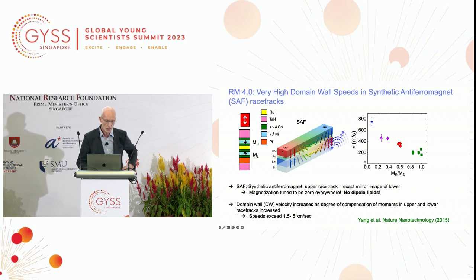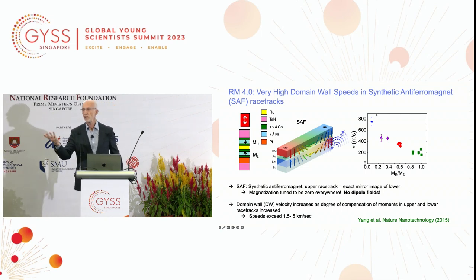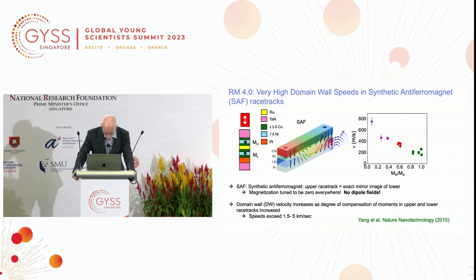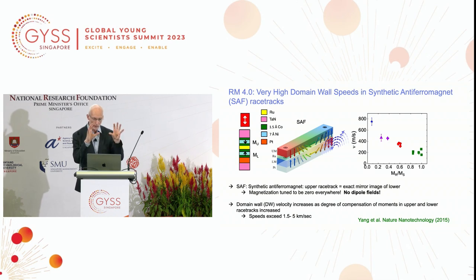It turns out if you take a thin layer of ruthenium, 7 angstroms thick, it will give rise to this amazing strong antiferromagnetic coupling, so we can make this mirror copy. By making this mirror copy, we discovered if we now pass current into this racetrack, the velocity of the domain walls at the same current density as we make it more and more balanced increases by up to a factor of 5 to 10. So now we can move these domain walls 5 to 10 times faster than we could have imagined when I first started this project in 2002. This is totally new physics, but it means we can move these domain walls extremely efficiently at high speeds, exceeding 1 kilometer per second, in these racetracks where there's no net magnetization, no dipole fields, perfect, the only way to make an application. Now, how do we see these domain walls?